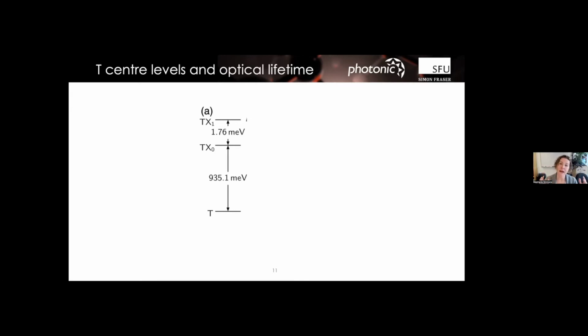Basically, it's a 3/2 object. So it would have 4 levels ordinarily, but that can be relatively sensitive to strain. And so what we actually have in the defect is a pair of levels in that first excited state, in that TX level, which we've labeled TX0 and TX1, and it's split by a couple, just under 2 meV. Now, that means that around 2 Kelvin, you can kind of ignore TX1 entirely, which is wonderful.